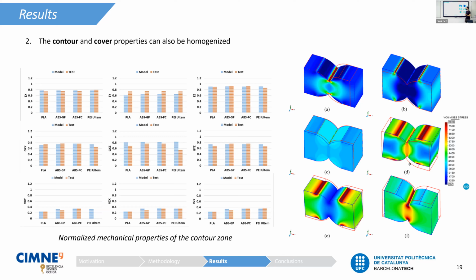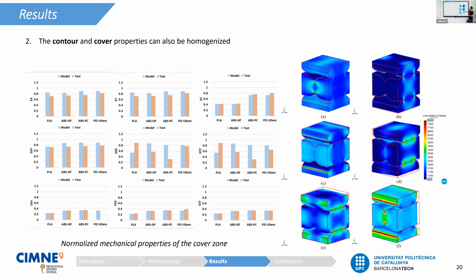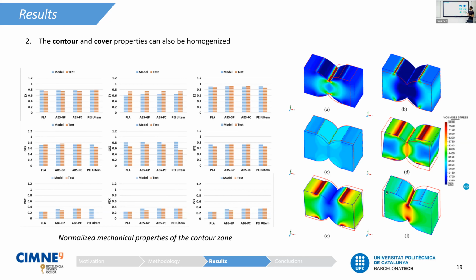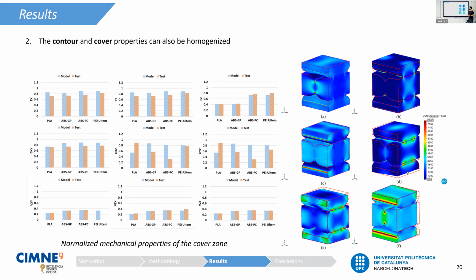We repeated this same analysis not only for the infill, for the inner zone, but also for the aligned and cross filaments. And we saw that this analysis can be performed as well via computational homogenization, because in here we are comparing in blue the computational results with, in red or green, the experimental results. And we can see that for all material properties, the relative difference is very low. Therefore, we can not only compute via computational homogenization the inner properties, but also the properties for the cover and the contour. These are the results in the previous slide. These are the results for the aligned filaments, meaning the contour zone. And these are the analogous results from the cover zone.